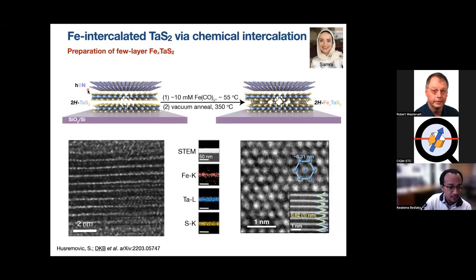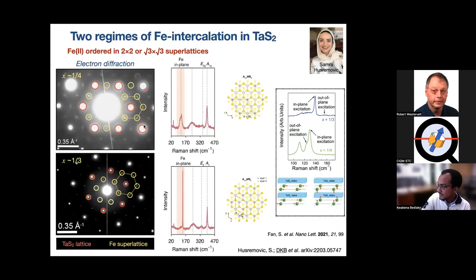Because I'm running out of time again, what we can do is we can prepare van der Waals heterostructures of these exfoliated host lattices. We can intercalate them with some, typically zero valent, precursors that then give up their ligands, enter the lattice, and lead to charge transfer with the lattice, and then in this case forming iron two sites in the interlayer. And those then assemble when we anneal them into superlattice structures that we can characterize by diffraction and that also give rise to very distinctive Raman features associated with the iron superlattice.